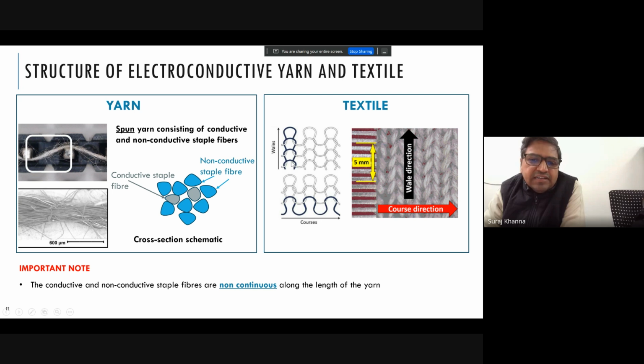Since this is in textile form, it has anisotropy. In one direction it has better connectivity, so it will have less resistance, and in the wale direction it has high resistance. In the course direction it's slightly lower resistance, but still in the high resistive state. And all these fibers are non-continuous in nature, as you can see from electrode 1 to electrode 2.